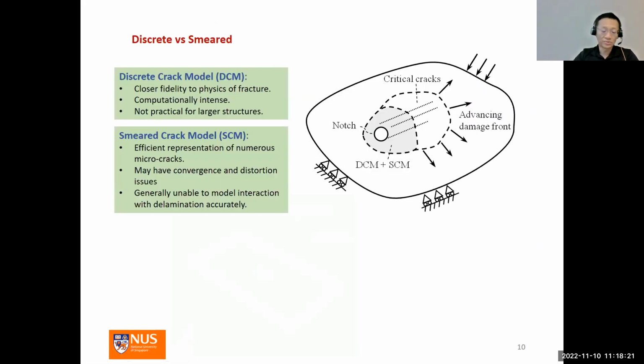So we now have two technologies with different advantages and disadvantages. The discrete crack model is closer to the physics of fracture, but it's computationally expensive, and therefore it's not so practical for application to larger structures. Smeared crack model, on the other hand, is relatively efficient, especially when numerous micro cracks need to be modeled. But it may have convergence and distortion issues and is generally unable to model interaction with delamination accurately. So in problems where there is delamination migration, these smeared crack models may not work.